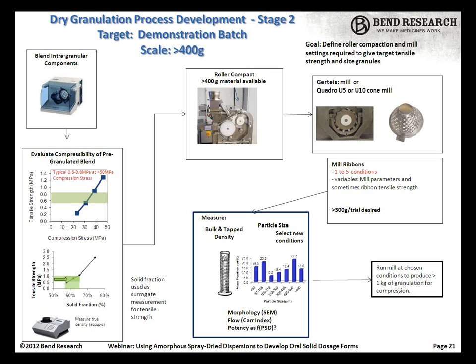So we have the parameters from our compression profile to determine the roll forces to achieve our ribbons of the desired density or solid fraction. So we'll run those at startup to make sure that we achieve our target solid fraction that we identified at our bench scale. And what we're really left then with is identifying the milling parameters to give us the desired particle size of the milled granules.